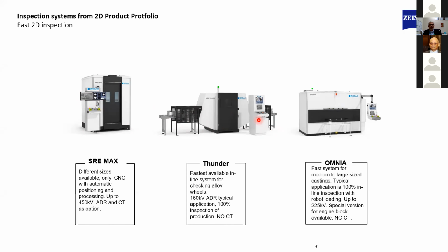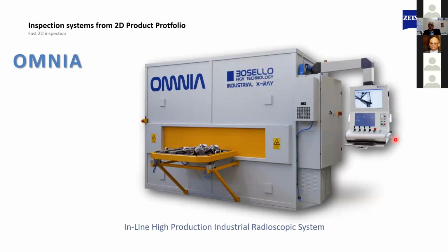And depending on the customer requirement, we can program the complete machine. And here we talk of a cycle time between 25 to 30 seconds per part, depending on how many images the customer requires. So on average, an 18-inch wheel will take about 30 to 35 seconds for one wheel inspection. And then this is an Omnia system for prismatic parts. It can also be completely kept on the shop floor. And with ADR software, you can do complete defect analysis. This is basically only for defect analysis.